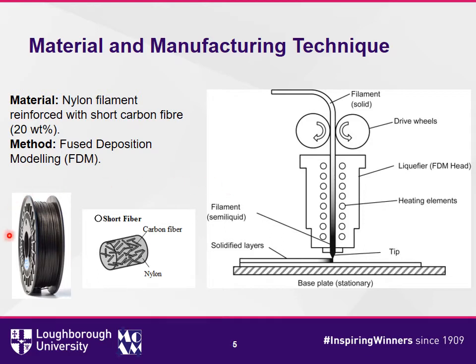For the research, nylon filament reinforced with short carbon fiber was selected, and the printing method was fused deposition modeling. This method heats the filament and melts it into a semi-liquid phase, which is then extruded through a nozzle. The material solidifies and adheres to the corresponding layer, forming a multi-layered composite structure. Nylon was selected as the material because it shows more plasticity compared to other polymers like PLA or ABS, therefore would absorb more energy through deformation before failure, and the addition of carbon fibers significantly increases the strength of the material compared to just the polymer itself.